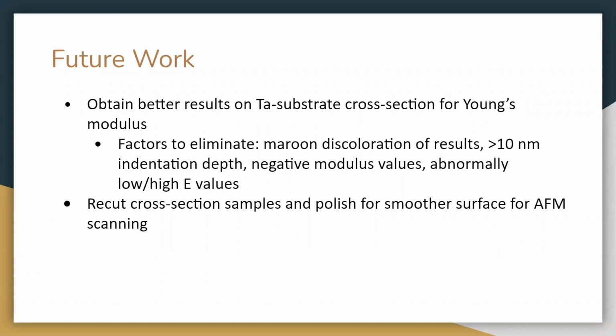So, future work on this project would be to obtain better results on the tantalum substrate cross-section for the Young's modulus. Some factors that occur during testing make it very difficult to verify if the scans are accurate or not: there's maroon discolorization of results, and the indentation depth of the tip. Oftentimes, it's higher than 10 nanometers when it should be less than 0.4 nanometers. And we also want to eliminate the negative modulus values as well as abnormally low or high Young's modulus values. So, as seen before, there was around 60 gigapascals for the tantalum when it should be around 170. And really troubleshooting the AFM can improve our results this way.